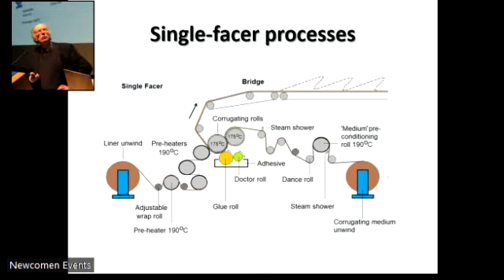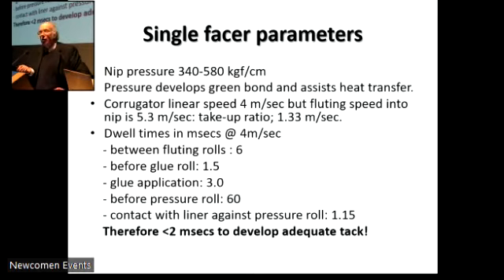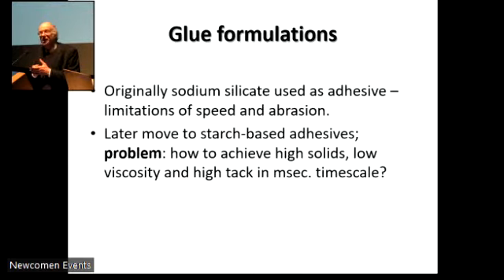Now, again, this is just a quick look at the single facer, because what we're aiming for is something which is stuck together sufficiently well that we can then take it to the next stage of the proceeding. But it's worth stopping and considering actually how extreme the conditions are in the single facer. The pressure in the nip between the second corrugator roll and the liner is about 340 to 580 kilograms force per centimeter, which is why modern corrugators are heavily enclosed, because there is no way your fingers would survive passage through the nip. The pressure is essential to develop the green bond, to actually shear down the components of the starch adhesive and make them stick.